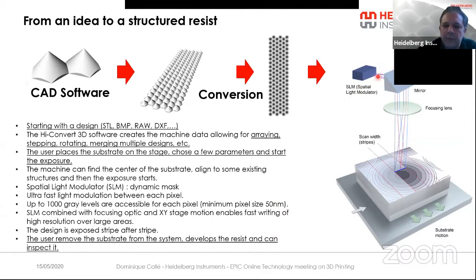So the SLM combined with focusing optic and the XY stage enables fast writing of high resolution over large areas. And when I'm talking about large areas, we have systems that are writing mask or grayscale mask up to 1.4 meter in one dimension. So this is not typical for R&D research, but this is for industrials. And then when the exposure is done, the user removes the substrate and then develops it, and then can inspect the surface of the photoresist.